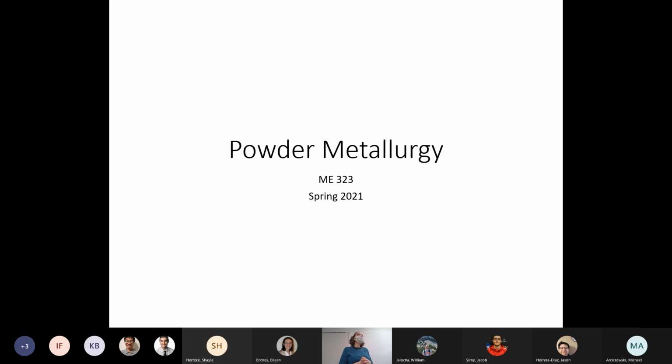So a reducing atmosphere generally has some hydrogen in there, and it would take any oxide that's there and remove it from the metal. Just a little bit of chemistry to throw in. But sintering is never going to be done in air. It is always done in vacuum, purely protective, or maybe a reducing atmosphere.